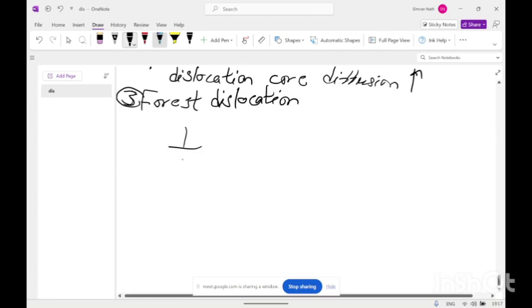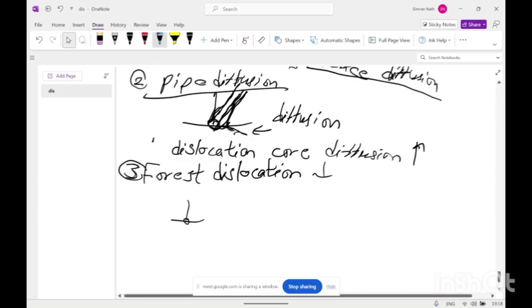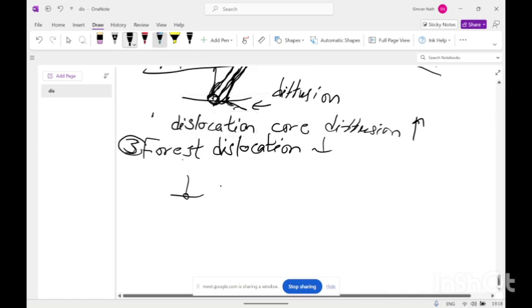As the dislocation moves through its active slip plane, through the pipe diffusion, the solute atoms will drain from the forest dislocation to the mobile dislocation. Means if there is a forest dislocation, with multiple dislocations, the atoms from that forest dislocation region diffuse to the mobile dislocation core, because the strain field of the mobile dislocation is higher, so it can attract the solute atoms more.